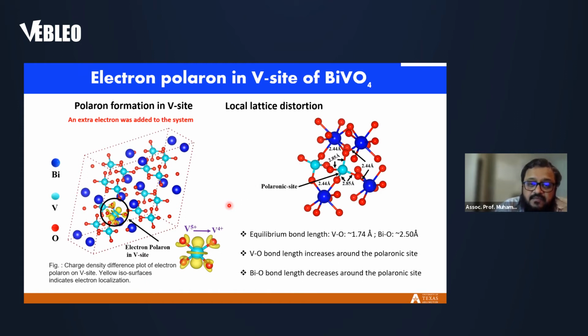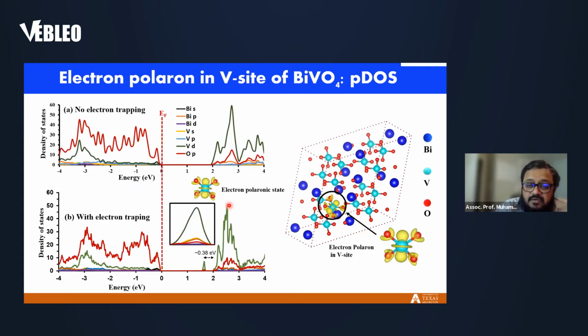And the third footprint, if we want to look, is at the electronic level. Compared to the pristine bismuth vanadate density of states, we see that the electron polaron formed about 0.4 electron volt below the conduction band minimum. And this is mostly formed by the vanadium 3d orbital. This is the amplified view of this peak.